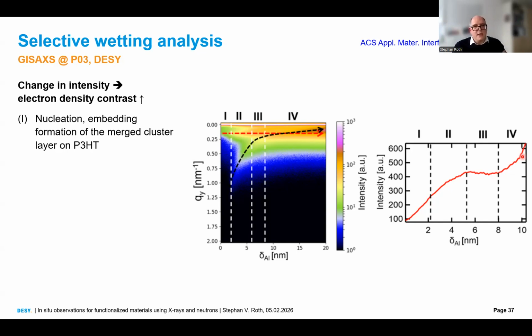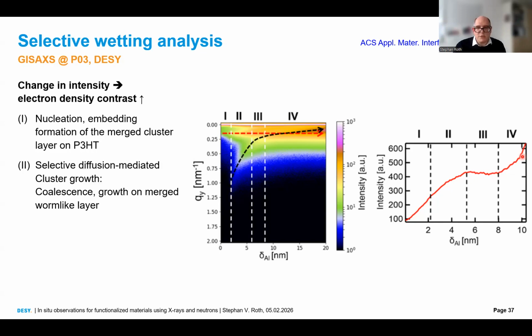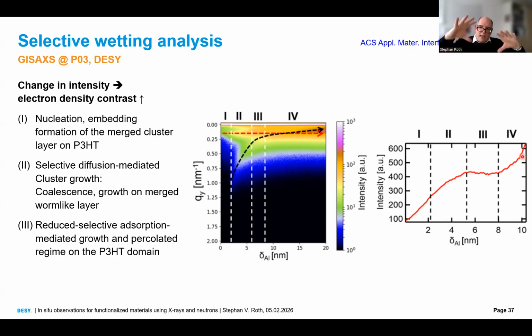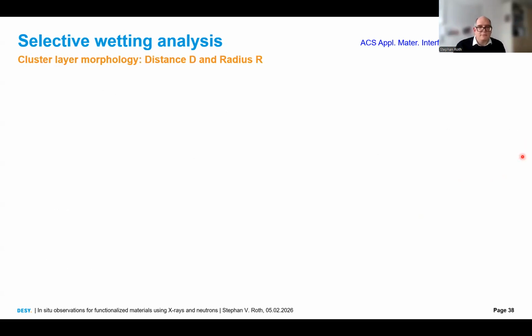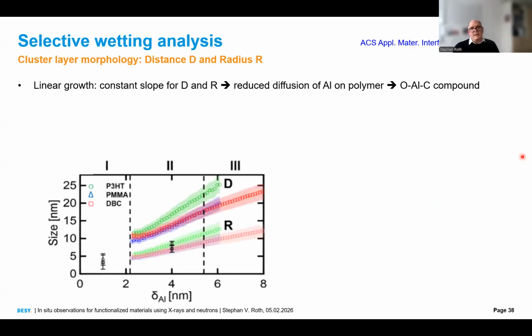We have first a nucleation and embedding formation of the merged clusters on P3HT. In phase 2, we have selective diffusion mediated growth. The clusters coalesce and grow on these P3HT worm-like structures. And then at one point, also we have growth on the PMMA layer. And finally, we have a percolated layer. Good. We can in all details find out distance and radius.